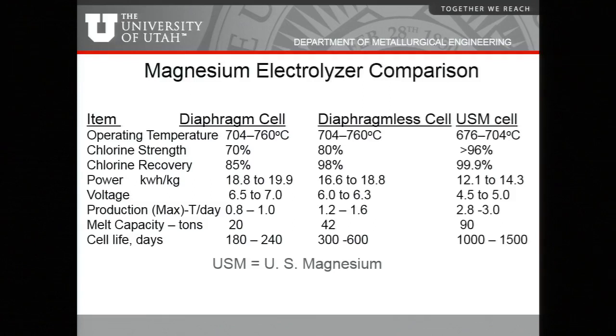And some of that is really tied to how they make their magnesium chloride and how they make it pure. They go through some fairly innovative processing to get rid of the very last remnants of magnesium oxide and to make sure that that mag chloride is anhydrous. If you've worked with magnesium chloride or with magnesium itself, you know it oxidizes very, very readily. And in fact, we can use it to take away oxygen from titanium, which really likes oxygen. Magnesium really, really likes oxygen. And so it's actually quite tricky to do this and to make it work and to become efficient. So they've made some nice inroads. How much more they can do in some cases on the efficiency side, I'm not sure they're really going to do a lot. But they are looking at doing expansions and tweaking what they already have.